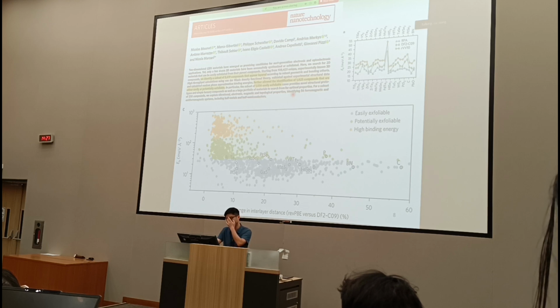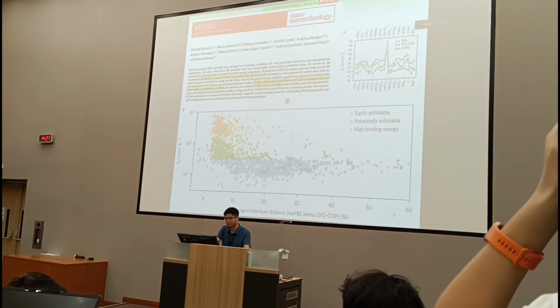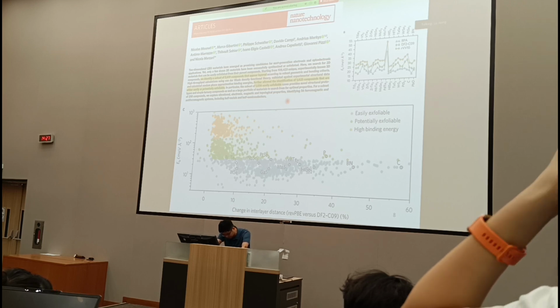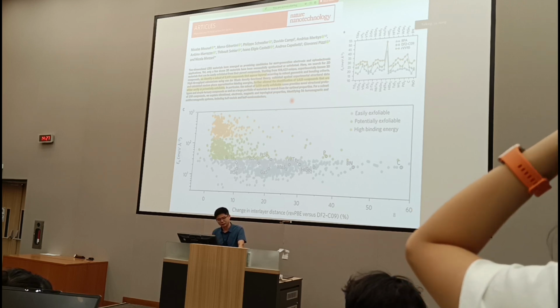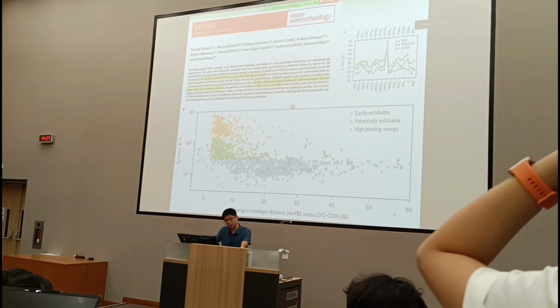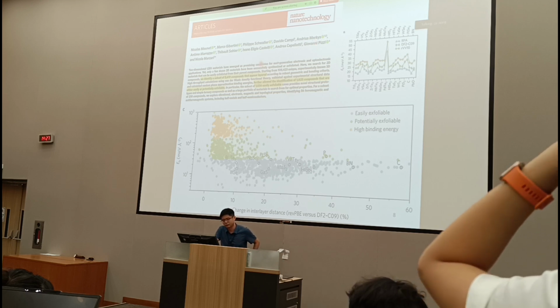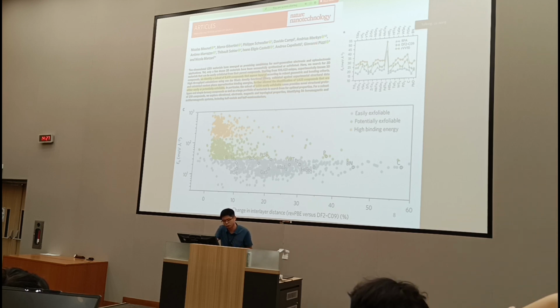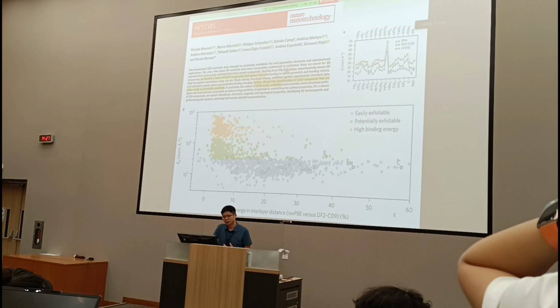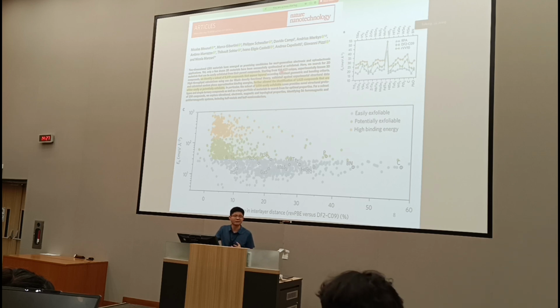Also nowadays we generate a sufficient amount of data, so we can use artificial intelligence for learning and to do some predictions. This is one of the early works published in Nature Nanotechnology that also used high-throughput computation to search through more than 1,000 unique materials that could potentially be candidates for 2D. So they calculate basically the exfoliation energies.